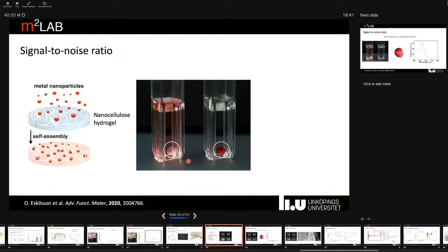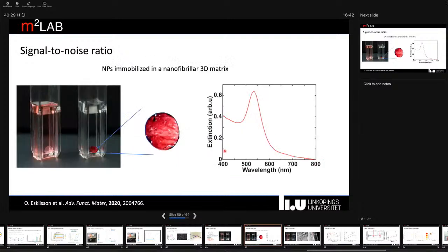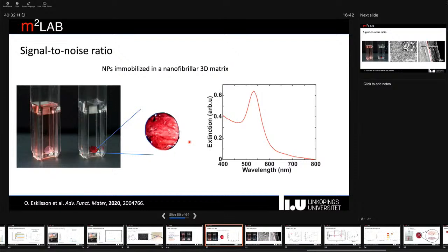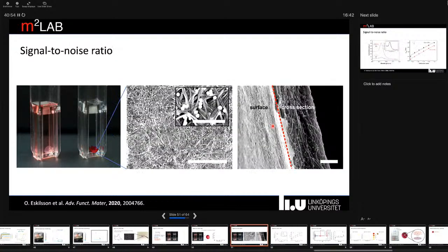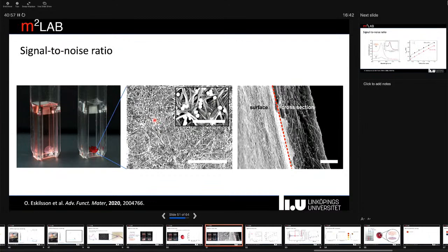So after some optimization, we were able to essentially make all these particles go from being suspended to being adsorbed in this membrane. And as you can see here, we end up with a substrate that is not faint pink, but bright red. We can also increase this intensity quite a bit more, but then you start to get a broadening of the plasmon band. But in this case, we have a very well-defined plasmon band. And this is due to the particles being fairly well distributed within this three-dimensional matrix, both on the surface but also throughout the entire volume of this hydrogel.